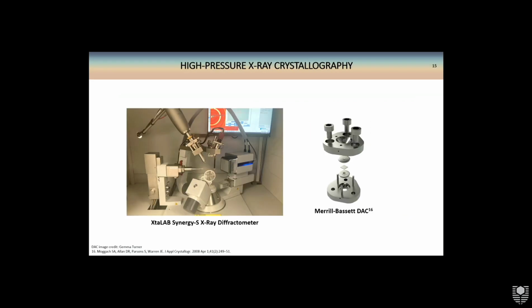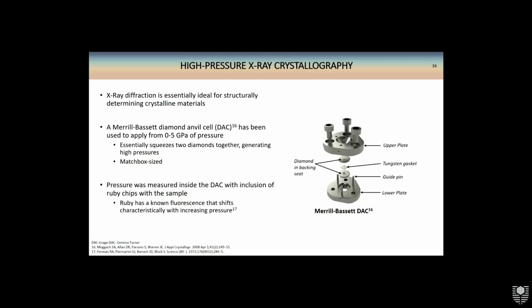So moving on to the experimental side of things, the work I'll be showing has been with X-ray diffraction, which is basically the ideal technique for structurally determining new crystals. And I've been doing all my experiments under high pressure from about 0 to 5 gigapascals with the use of a Merrill-Bassett diamond anvil cell.